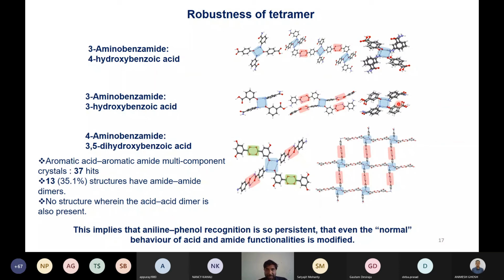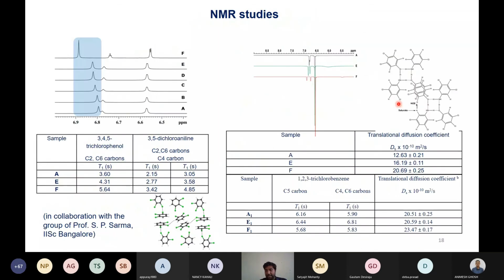So by looking at this persistent nature of these tetramers, we thought that it may be possible that these tetramers, these LSAMs, are observed in solution. So we did this study in collaboration with the Professor S.P. Sarma group in IISc Bangalore. And we showed, starting from the left, this is the 1D NMR study, where A is the highest concentration of this molecule. We have taken the 3,5-dichloroaniline with 3,4,5-trichlorophenol co-crystal structure as a model compound for this study. And we are going from A to F in dilution.